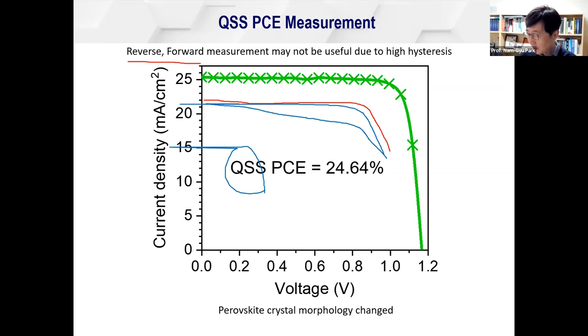Well, I look at the Pb2+ lead toxicity, we should not hide this kind of toxic issue. We have to disclose it. Even though, for instance, methyl ammonium lead iodide is under moisture instability, moisture can decompose this material to produce lead iodide, PbI2. And the solubility product of PbI2 is about 10 to the minus 8. That is still low, a very low dissolvability of PbI2 in water.